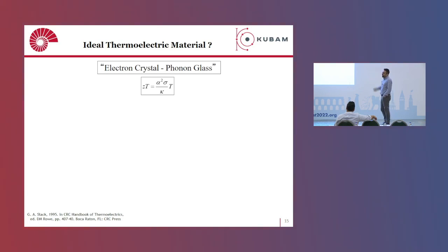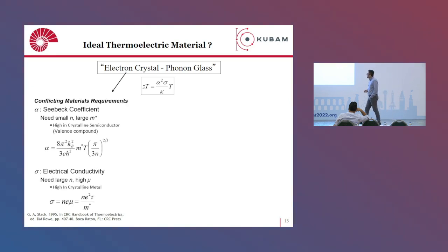Okay, so what are the ideal thermoelectric materials? The phonon glass electron crystal concept describes these materials. It says the material should be a very good electronic conductor like a perfect crystal, but at the same time have low lattice thermal conductivity like glasses. This is hard to make in one material because of conflicting transport coefficients. Metals have large carrier concentration, but when a material has a large carrier concentration, it has a low Seebeck coefficient. On the other hand, semiconductors generally have low carrier concentration and large effective mass.